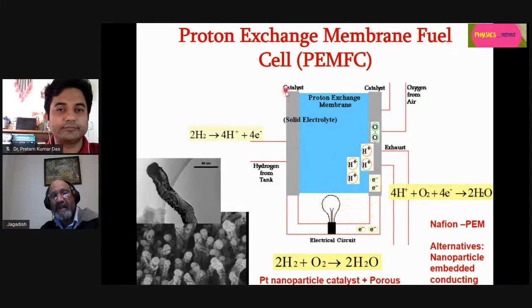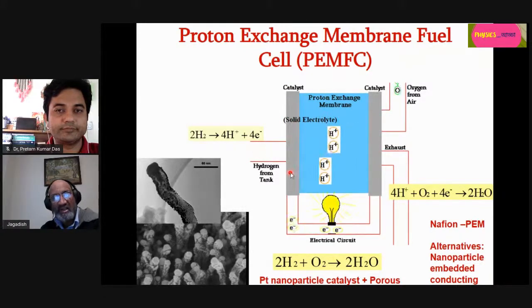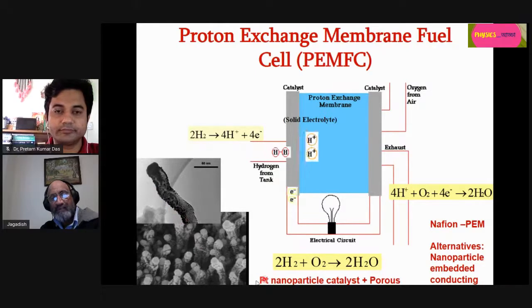And people have been using platinum as a catalyst, but platinum is very expensive. And my colleagues, Professor Rod Boswell and Professor Christine Charles at ANU, they are plasma physicists. They have really made use of carbon fiber, and they deposited some platinum nanoparticles using plasma processing. They're able to show that the properties of these particular electrodes are as good as that of the planar sheet of platinum catalyst or so. That means it can reduce the cost quite significantly.